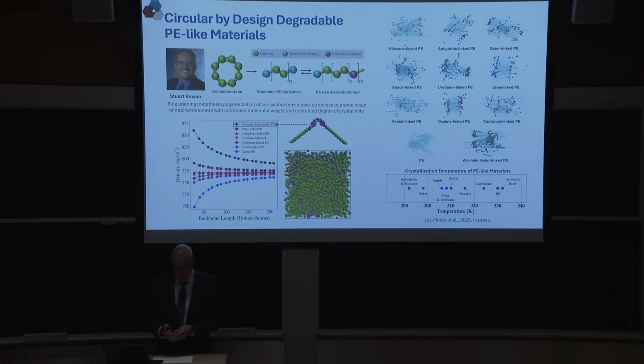Using simple models, you start to design or to measure things like density, melting temperatures, crystallization, viscosities, etc. And what you find is that these switches that you put in here, they actually can alter the rheology in major ways. They serve as hinges that you're putting in. The flexibility of the molecule changes dramatically, and the properties are completely different. And perhaps more importantly, what you find is that the moment that you start shearing or putting the system in extensional viscometers, they start to degrade. The molecular weight goes down very, very quickly.